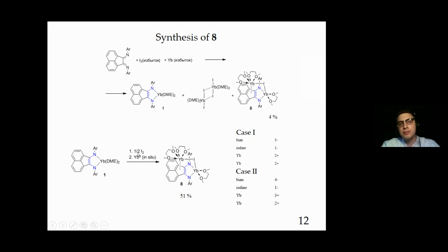a very active ytterbium metal from the corresponding ytterbium diiodide, from the equivalent of ytterbium diiodide and 2 equivalents of potassium graphite. And in reality, this resulted in a quite high yield of compound 8. This compound is tricky because there are possible 3 isomers.